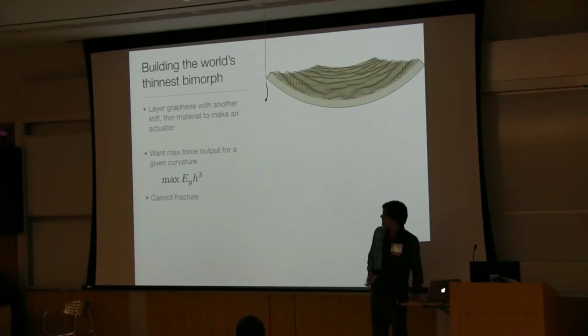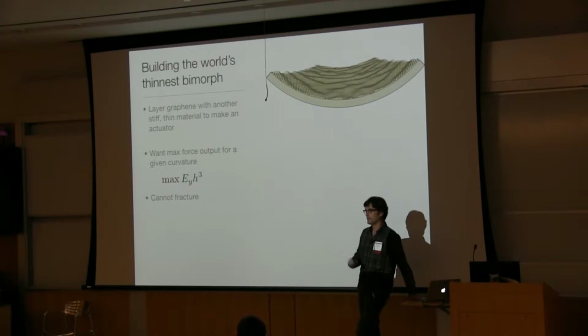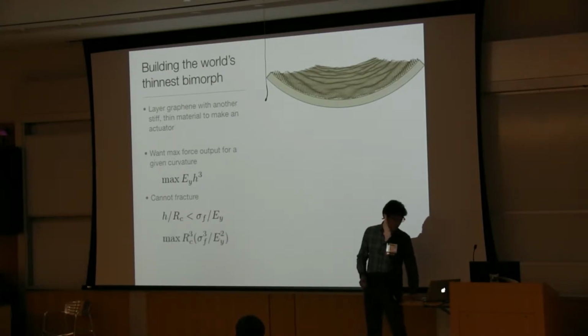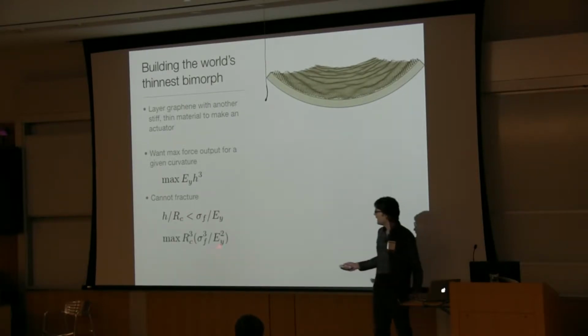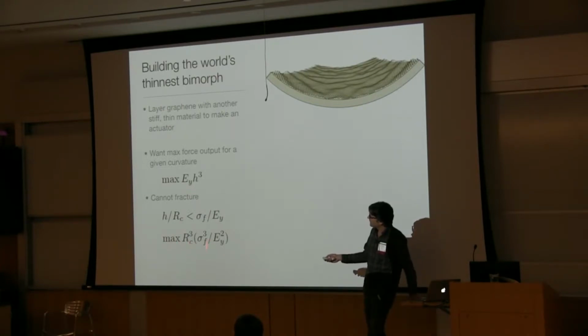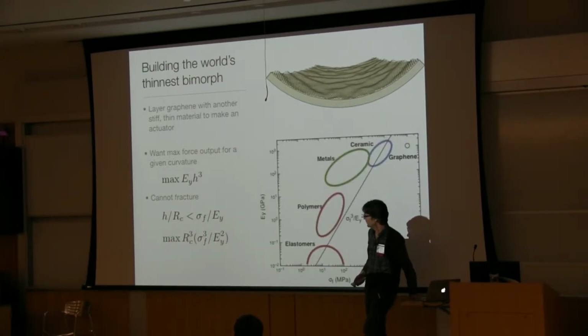Now we have a constraint here, which is that we don't want the actuator to fracture. Everything's got to be elastic. So that means that we need the strain inside the layer, the thickness divided by the radius of curvature, to be less than the fracture strain for a given material. And you can combine these two equations, and it tells you that really the thing you want to maximize is the product of the radius of curvature cubed, but this is just given to us. So the material thing we want to maximize is the fracture strength squared divided by the Young's modulus squared.